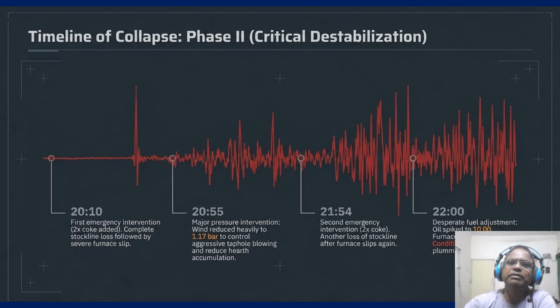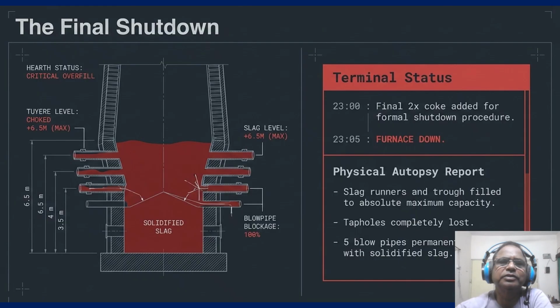And coming to our very important slide on the final shutdown. Look at the red cross section of the hearth on slide 7. At 2305, the furnace was officially down. The status was terminal: hearth critical, overfilled, tuyere level choked, and the slag level at its maximum 6.5 meter limit, we can say. The visual shows the solidified slag filling the blowpipe and the hearth area being completely lost. The physical autopsy report on the right confirmed that the slag runner and the trough were filled to maximum capacity.